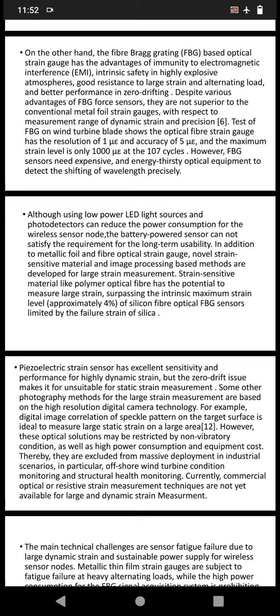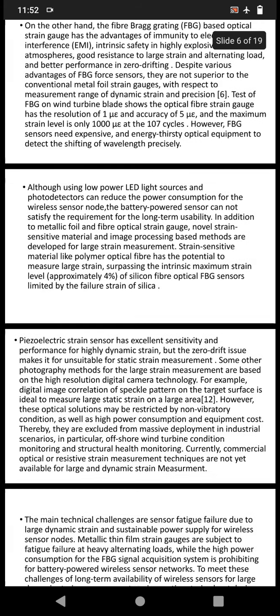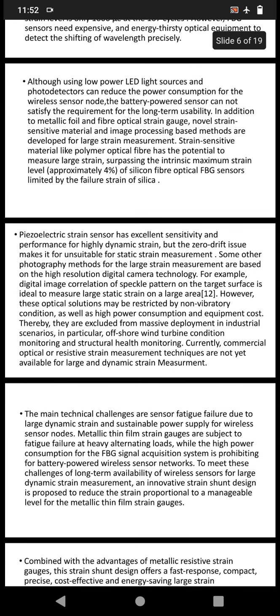Strain sensitive material like polymer optical fiber has the potential to measure large strain, surpassing the intrinsic maximum strain level, approximately 4%, of silica fiber optical FBG sensors, limited by the failure strain of silica. Piezoelectric strain sensor has excellent sensitivity and performance for highly dynamic strain, but the zero drift issue makes it unstable for static strain measurement.